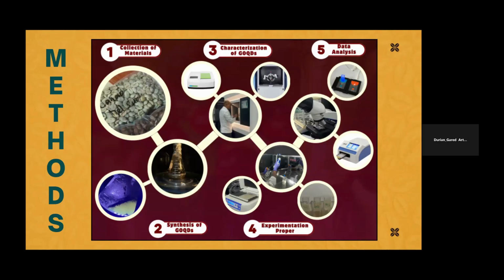Then, the synthesis of GOQDs happened by adding 100 ml of 1% hydrogen peroxide to 1 gram of black carbon and stirring thoroughly. After mixing, the black carbon and hydrogen peroxide mixture was placed in a microwave oven and irradiated at 600 watts for 2 minutes with 30-second cooling intervals. This process created GOQDs, which are nanoscale graphene sheets measuring 2 to 30 nanometers in size. The mixture was then purified to isolate the GOQDs from unexfoliated materials and larger graphene sheets using thorough filtration, enabling further characterization.